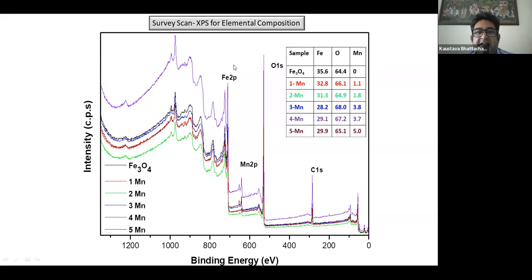So we can check that for Fe3O4 we get the Fe2p peak and the oxygen peak, and for the doping of manganese we get the different manganese peaks also. We'll always be getting a carbon 1s inadvertently, and we get other peaks also which are not marked here. I mean the other orbitals for the iron, manganese, carbon or oxygen, all are there. So if we do a qualitative analysis, what we get is that if I do almost 1% manganese doping, my surface has got almost 1% doping. If I have 2, 3, 4, 5, we get a good picture with this system.